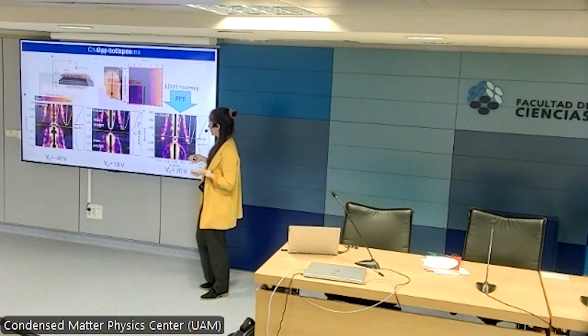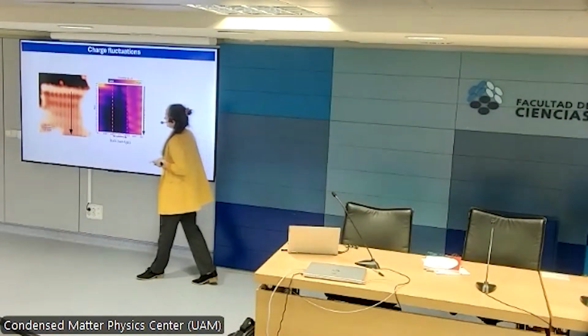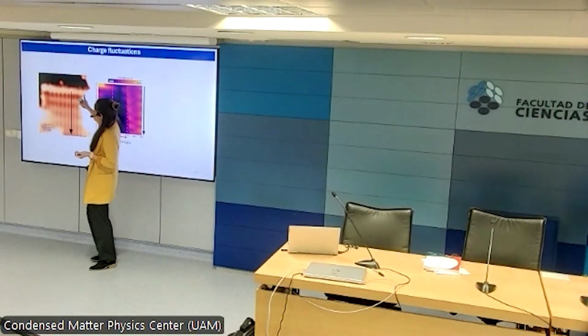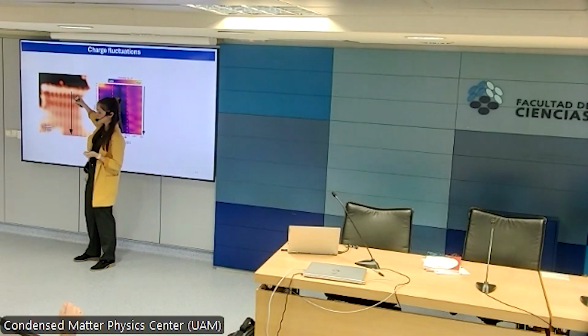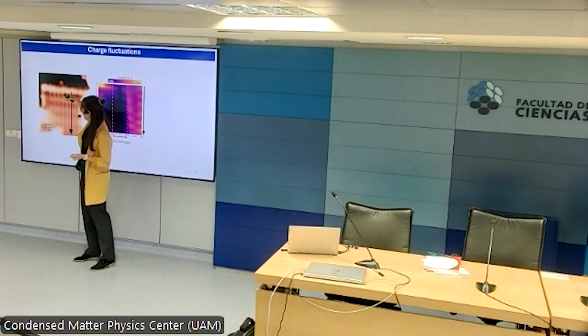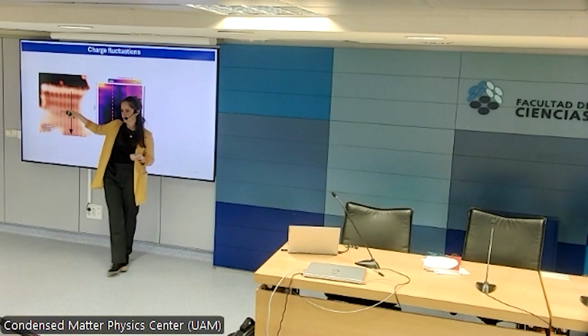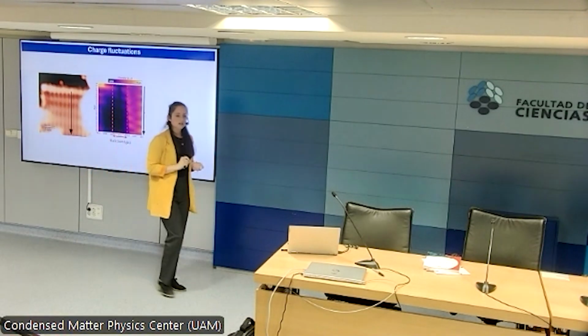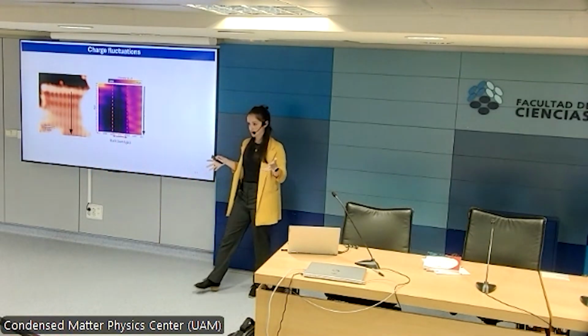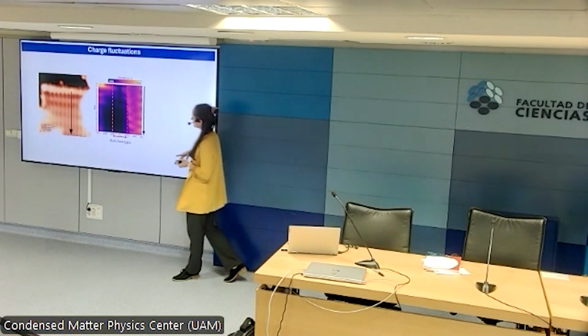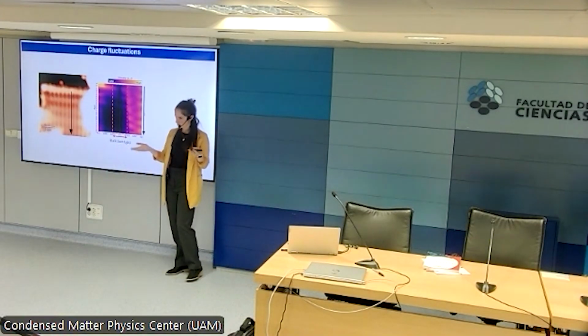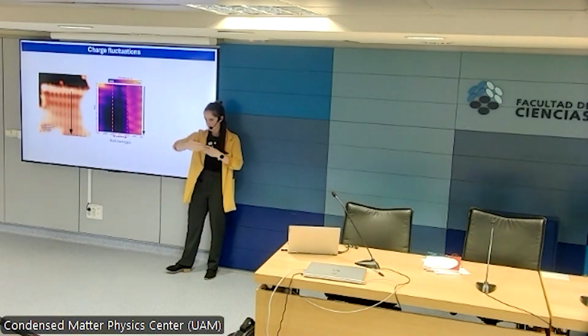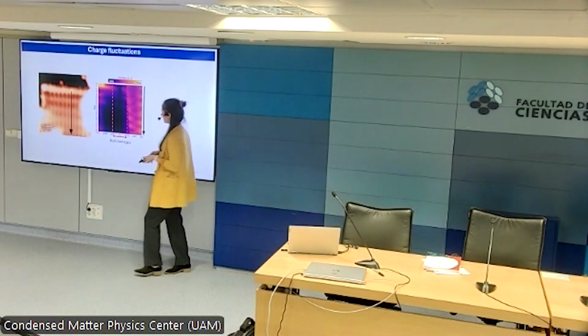Last thing that's left to do is to see if we can see the condensate and the excitonic collective modes. Now, if you look at this STM picture here, you can see that this is at the edge of an island. This is a very bright line that corresponds to the topological step edge. But you can see that the density of states oscillates bright and dark, going away from the edge. This would be your signature charge density wave. But it could also be Friedel oscillation or quasi-particle interference or scattering from the edge. Call it whatever you want.